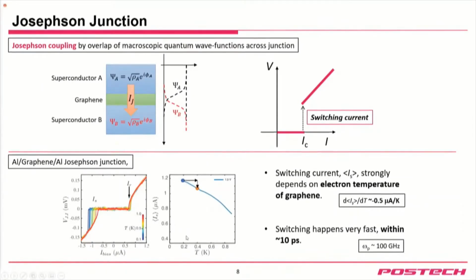So at the lowest temperature, the IC is something like here. And basically, this is the temperature dependence of the switching current. At the base temperature, we have about 1.2 microamp critical current. If we bias the junction with 1.1 microamp, which is smaller than the critical current, then the Josephson junction will stay in a zero voltage state.